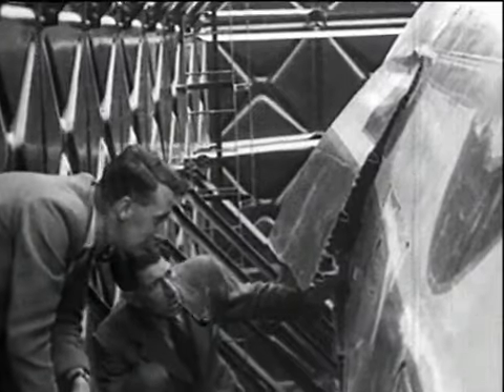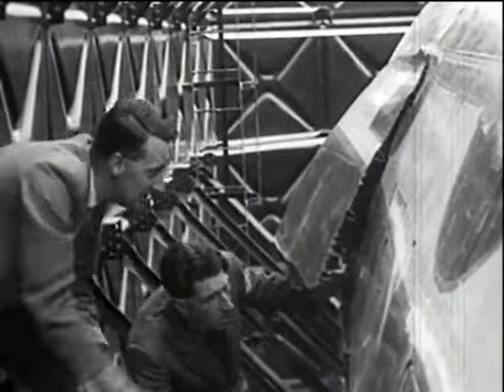The tests then continued. When the equivalent total life was about 4.5 times that of the Elba Comet, a further failure occurred, a crack near a window developing rapidly, and the port side of the cabin was ripped open for a length of about 15 feet. This third failure confirmed that the structure around escape hatches and windows was vulnerable from the fatigue aspect.